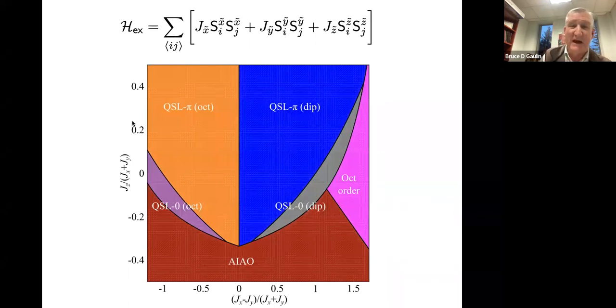But the point remains that a lot of this phase diagram is occupied by quantum disordered states. Now, the bottom of the phase diagram is not. The bottom of the phase diagram are these non-collinear Néel states. This is a dipolar non-collinear Néel state in red, and this is an octupolar ordered state, the equivalent of an all-in, all-out state but for octupoles, in this pink on the right-hand side. So that's the phase diagram that's expected.